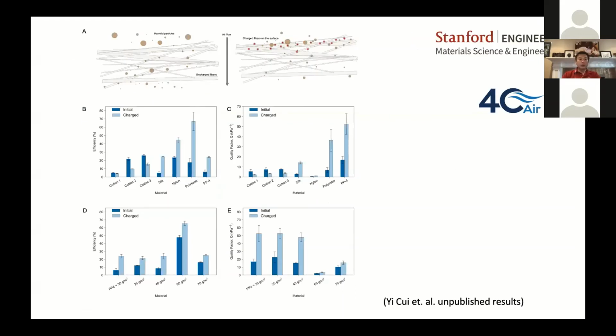So now right here, let me see. I lost my cursor. So now right here, I want to show you these different materials, cotton, silk. We basically charge up all of these fabrics using the static charge. And for each fabric, left-hand column, this bar chart, and the right-hand side is before and after. I want to point you to the polypropylene. Polypropylene has the biggest improvement in the before and after comparison, because polypropylene can be charged with static charge easily. Also, nylon is also good. Silk is good also. Cotton is not good.